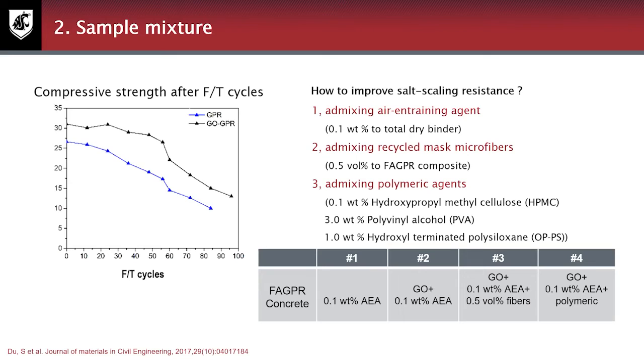Here we propose 3 strategies. The first one is to add mixed air entraining agents, which will introduce lots of tiny bubbles and then improve the freeze-thaw resistance. The second strategy is to add mixed fibers. Here we propose to use this fiber to increase the integrity of the microstructure after salt scaling. The third one is to add mixed polymeric agents, and this strategy is based on our previous publication. These 3 polymeric agents will slow down the water absorption and increase the water contact angle, and that means to make the samples repel water and keep it out.